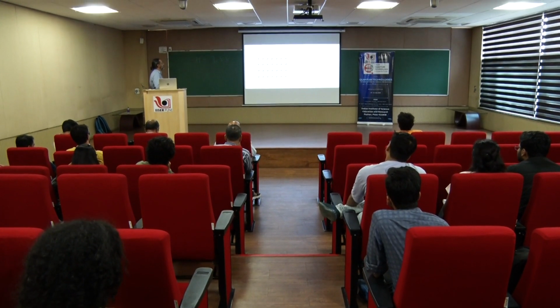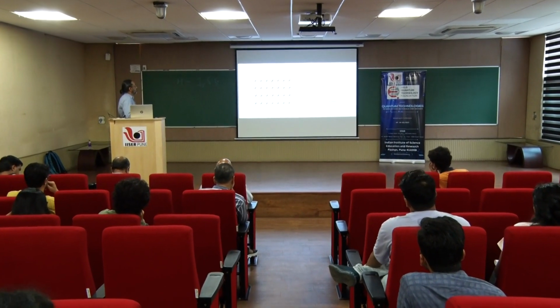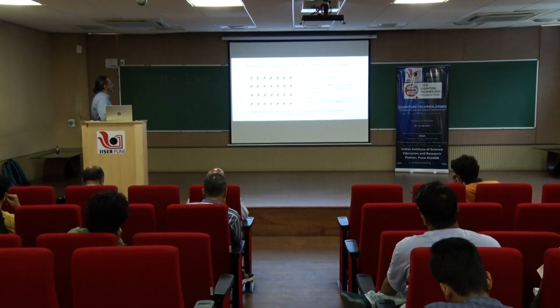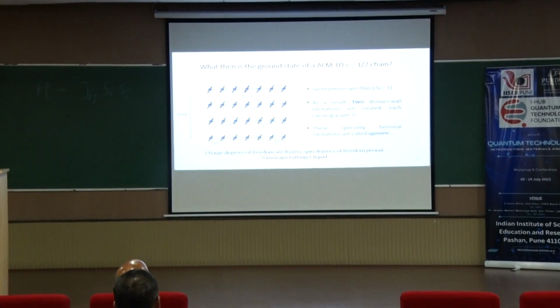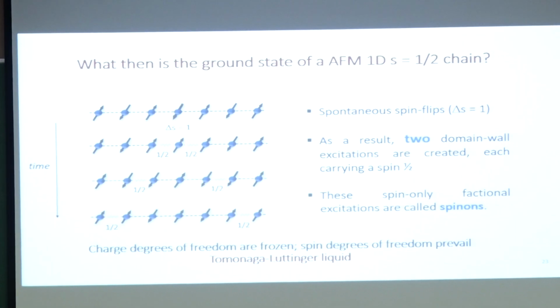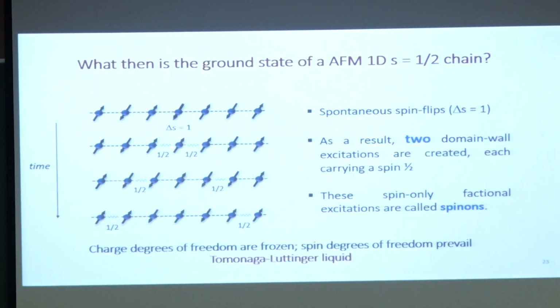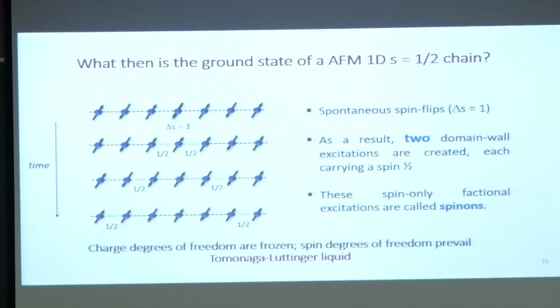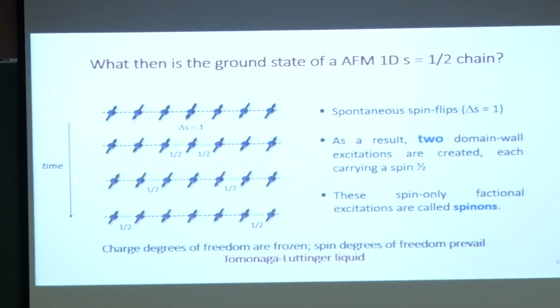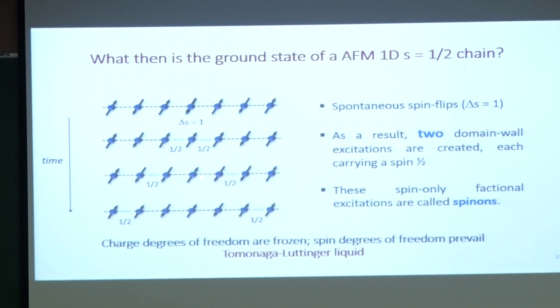Okay, so each one is carrying a spin 1/2. How do we know that? Because this section has a net spin 0, but this same section, when you have flipped one of the spins, has a spin 1. So the net change of spin is 1, and this is shared by these two domain wall like excitations. Why domain wall like? Because these excitations can now propagate along the length of the chain without any additional spin flips, which means without costing any additional energy.